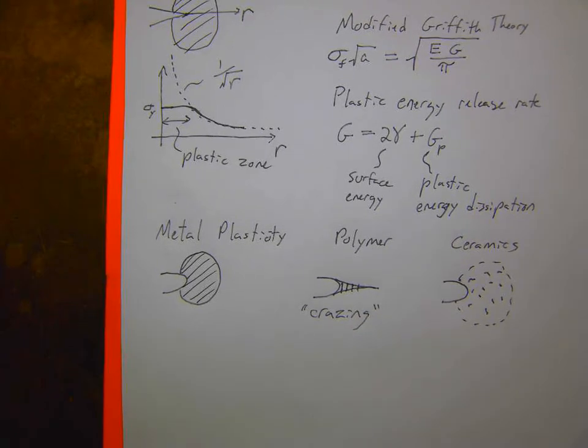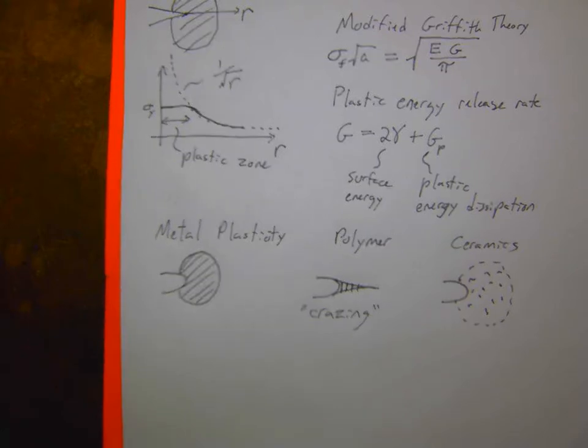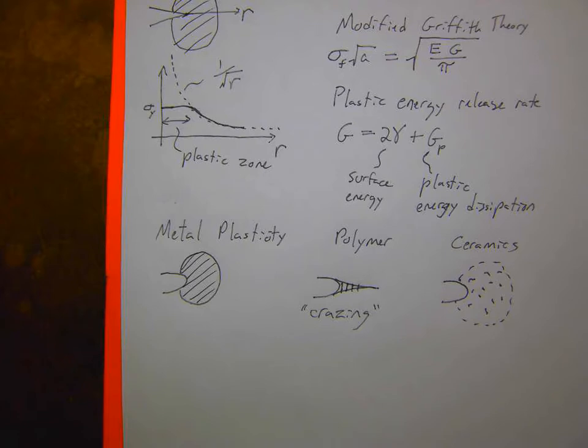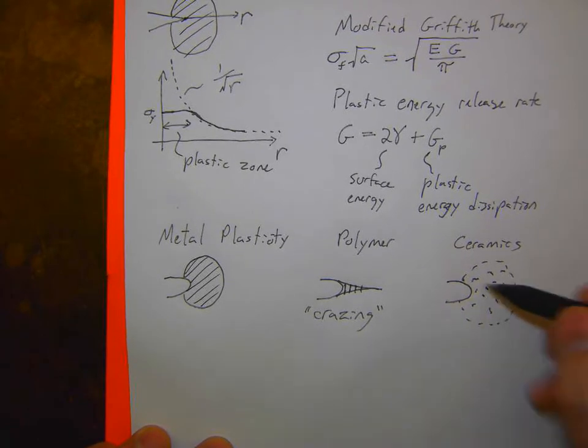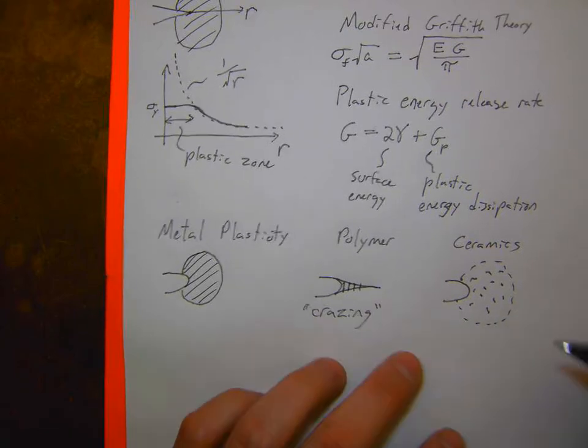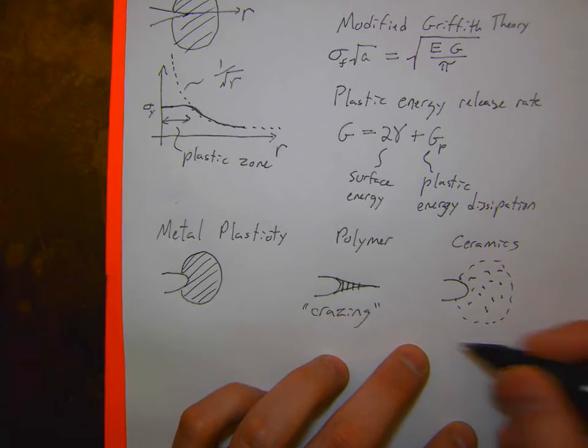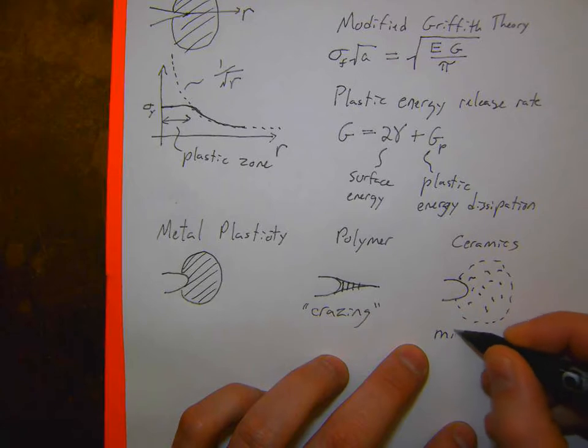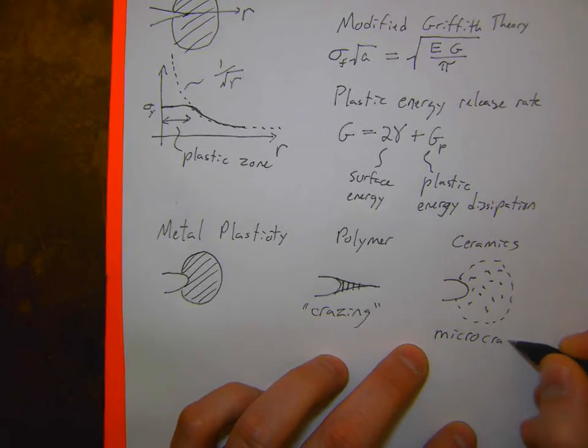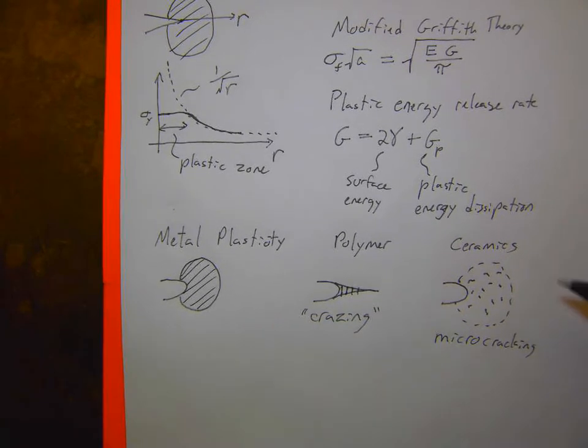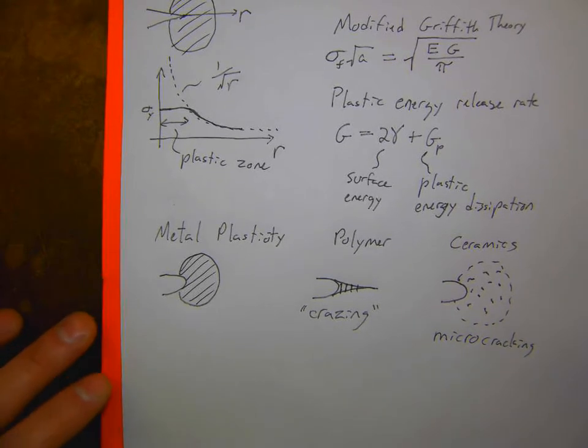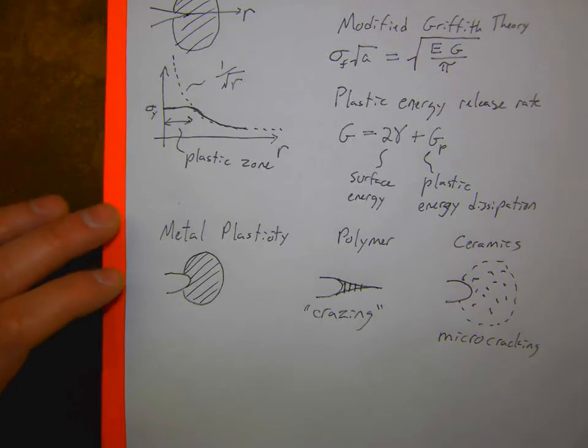So for glass or for single crystalline brittle materials, glass doesn't have a microstructure, it's just amorphous, and single crystalline silica is single crystalline, so there are very few defects, so none of these microstructural processes can happen. But in a normal ceramic, you can get this microcracking phenomenon that actually absorbs some of the energy. Actually, in ceramics, there's a whole lot you can do to absorb energy, but this is one of the more prevalent ones.